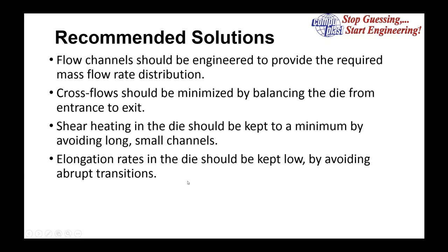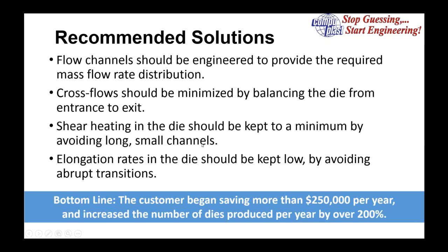The solutions are to have flow channels properly engineered for the right polymer distribution, minimize cross-flows, avoid excessive shear heating by keeping high-shear areas short and avoiding small correction channels, and avoid high elongation rates by avoiding abrupt transitions. This will make dies less sensitive to lot-to-lot polymer differences. This customer began using proper engineering and saved over $250,000 per year, while also increasing the number of dies they could make in a year by over 200%.